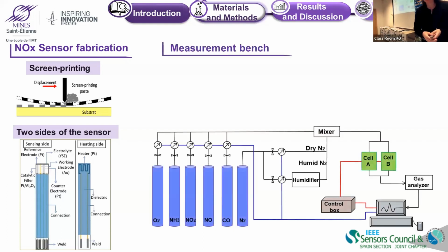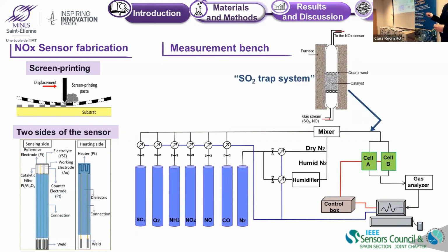The efficiency measurements of the sensor are done with this classical test bench, and we add, after the mixer, the SO2 trap system. So the stream will pass into the trap and then descend to the sensors. We also add an SO2 cylinder. We can also notice that we have a gas analyzer at the outlet in order to check the concentration at the end.